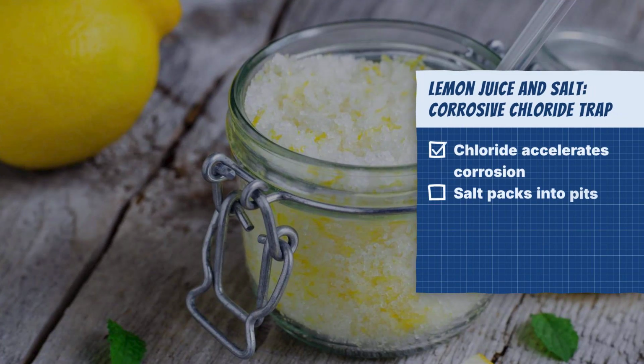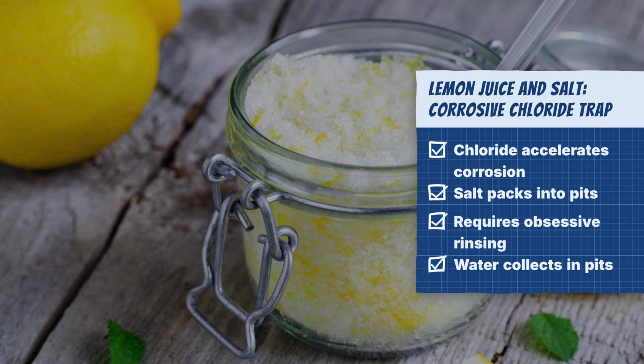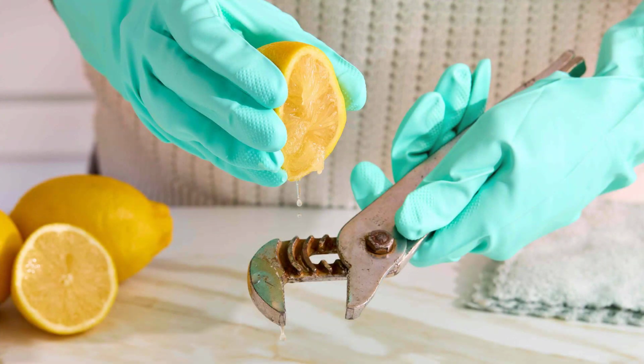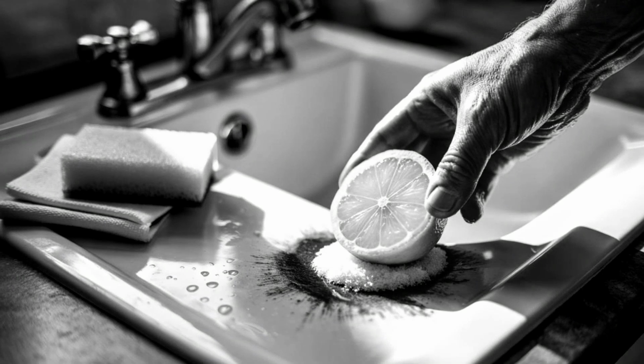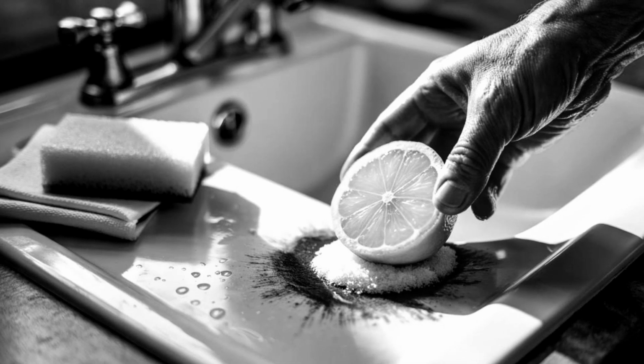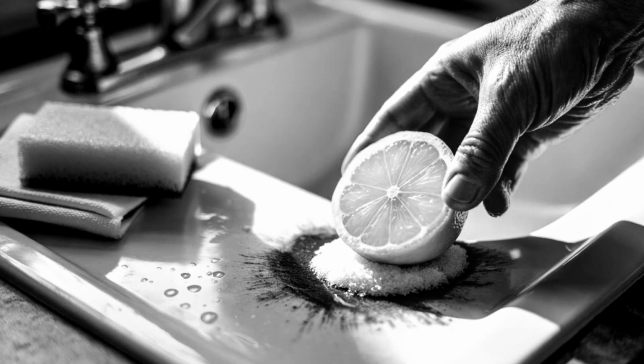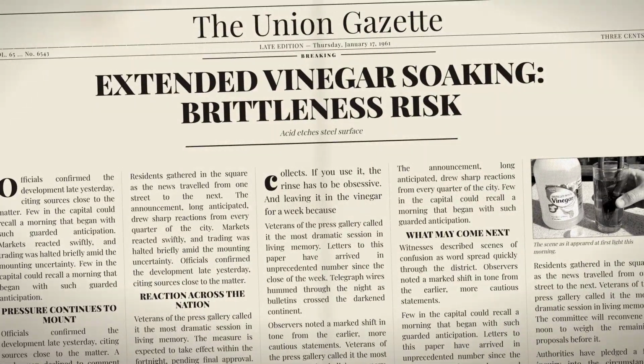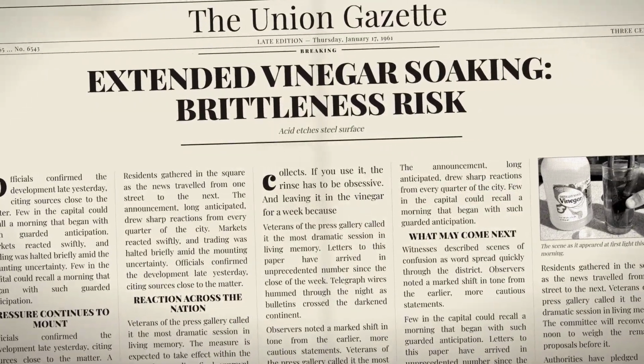The lemon juice and salt scrub. Weak citric acid combined with an abrasive, which sounds sensible. The problem is the salt. Chloride is one of the most aggressive accelerators of steel corrosion there is, and unless every last trace is rinsed out of every pit, what you have done is pack the most corrosive material in your kitchen into the exact places where water collects. If you use it, the rinse has to be obsessive. Then there is leaving it in the vinegar for a week because you are busy.